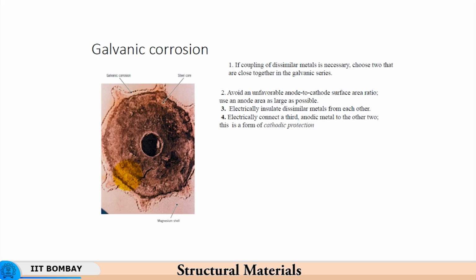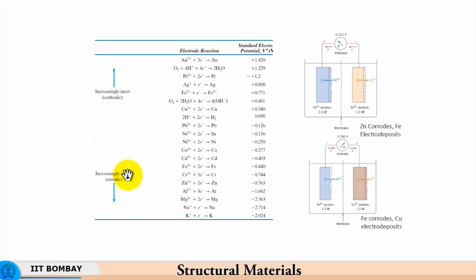So, if you do not want a galvanic cell to get formed between magnesium and steel, then the first thing is to avoid an unfavorable anode to cathode surface area ratio, meaning the area of the anode should be as large as possible. Electrically insulate dissimilar materials from each other. So, as long as we do not let this electric circuit get completed, there will be no reaction here. When we want to make a battery, you need to make sure that this circuit is closed, because now you want to control corrosion, and particularly if it is a rechargeable battery, you can get this anode material back during the process of charging.